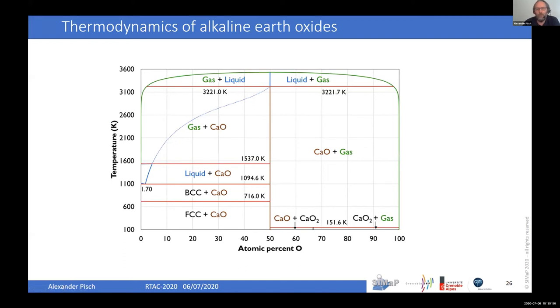And this is just to show you that it perfectly matches the experimental values, which, I didn't plot it, but you can trust me, they are here, the liquid solubility in pure calcium, and here you get the melting point. And that's something that's probably worthwhile just to discuss for 1 minute. The melting point we calculate is the congruent melting point, but this one is something that you can never measure, because the melting point depends on the oxygen partial pressure.